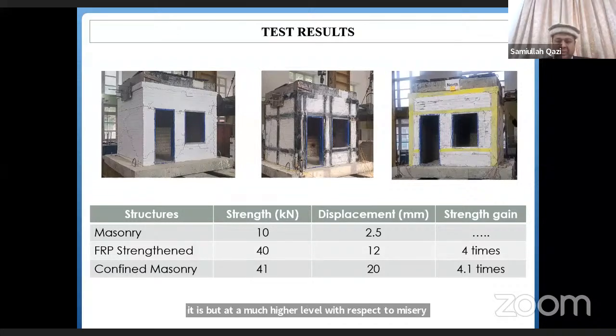So we can safely say that the FRP strengthening that we have adopted has improved the capacity of the existing structures almost 4 times. And as this technique requires less labor, within 2 to 3 days we can have the structure again in service. So therefore, we can safely say that it should be the technique used for existing structures to strengthen them. So now if you have some question relevant to this topic, you can ask me.